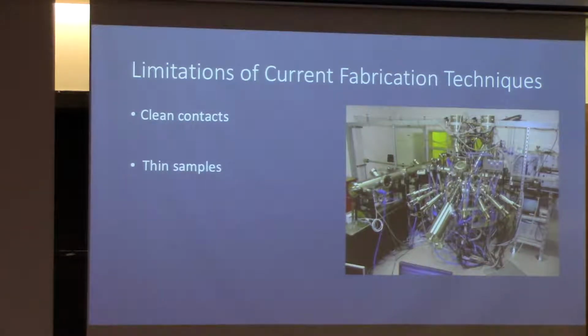You also have to make sure that your sample is very thin, because when you shine light on your material in order to measure this response, the light only penetrates so far into your material. And if you've got all this extra material on the bottom, the electrons of the current that you're making can scatter down there, and then you don't measure that as part of your response.